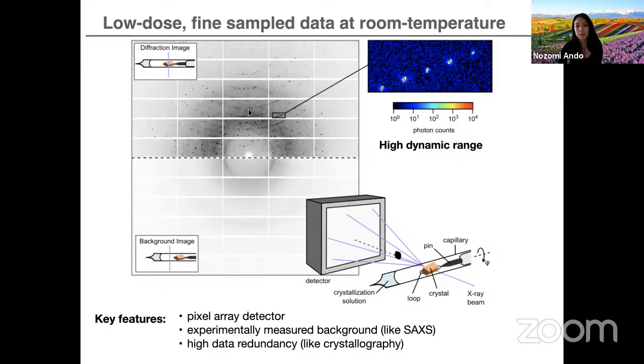But we also wanted to make use of some of the key features of the newly available pixel array detectors. That included the fact that in addition to having a high dynamic range and a very small point spread function, these detectors have really fast frame rates. And so we can collect finely sampled data. Specifically, we collected low dose, finely sampled data. And what that means is, unlike the Casper and Clarage image that I showed you before, that was a long exposure, we take short exposures to avoid radiation damage. But we collect a lot of them as we're rotating the crystal and finely sample them.